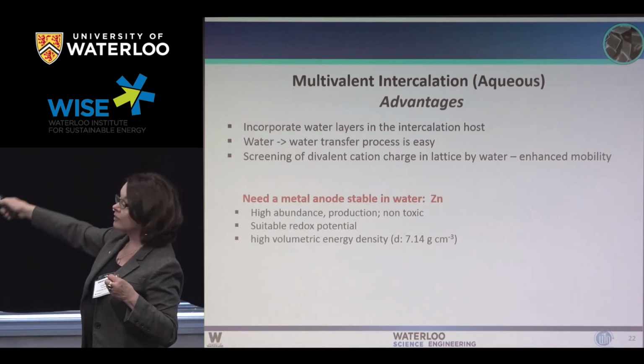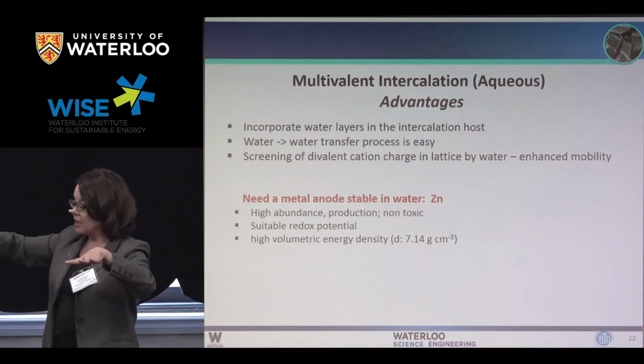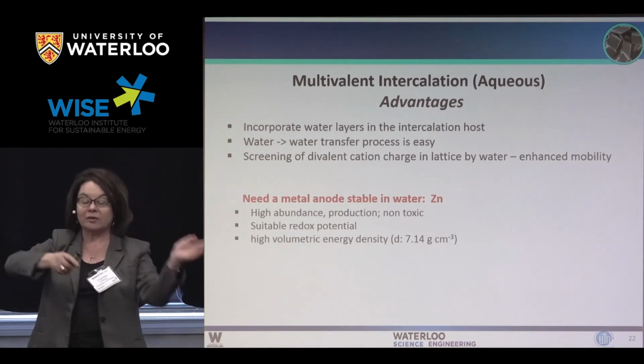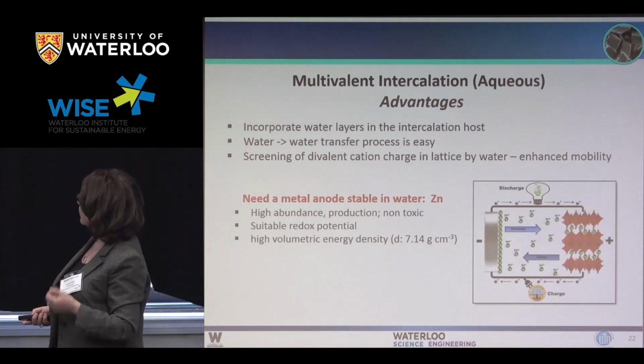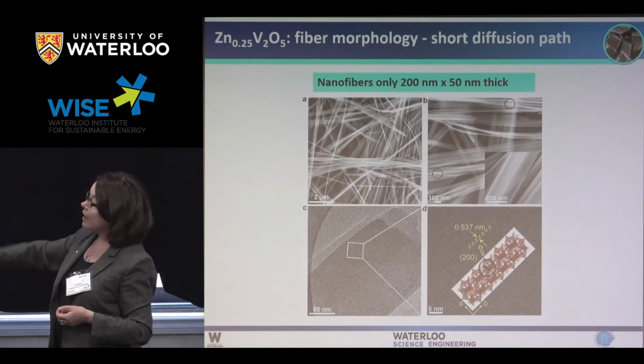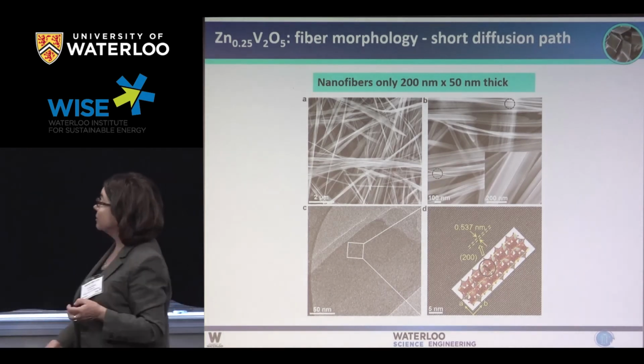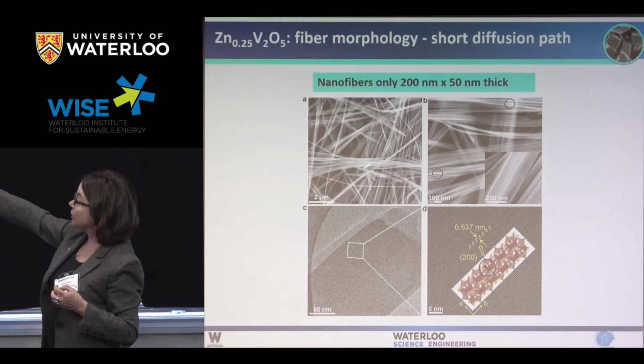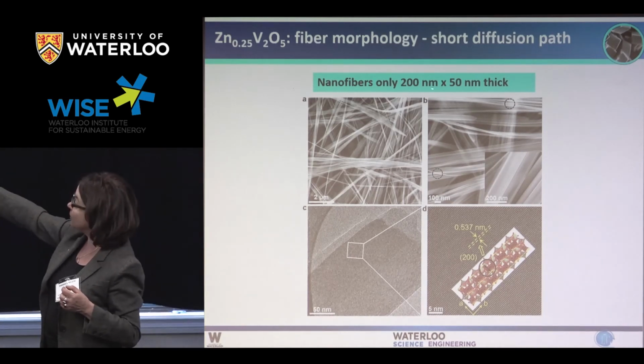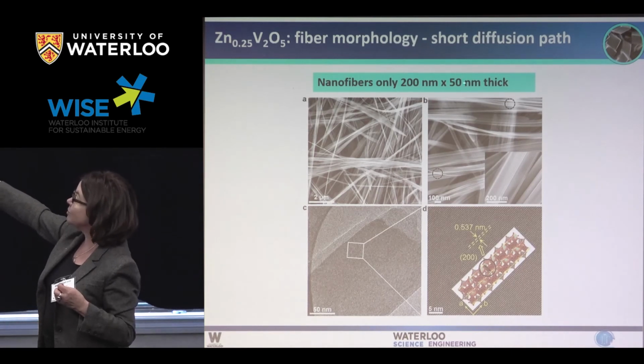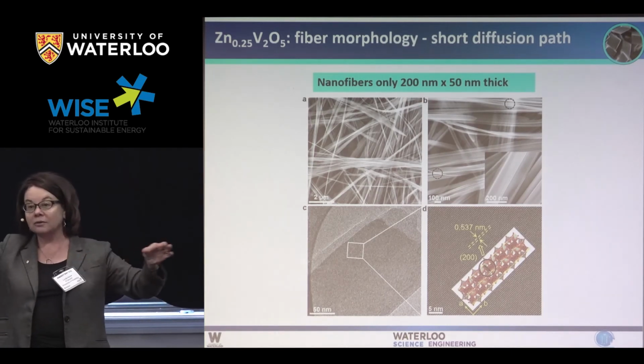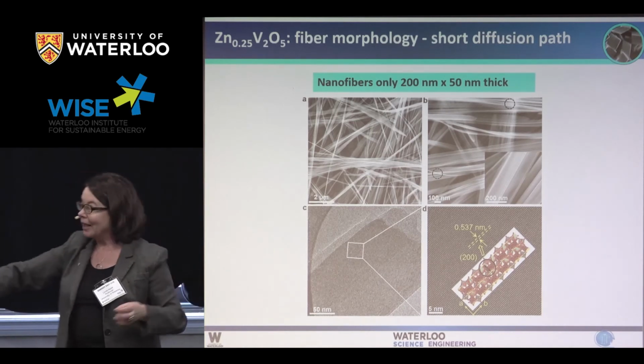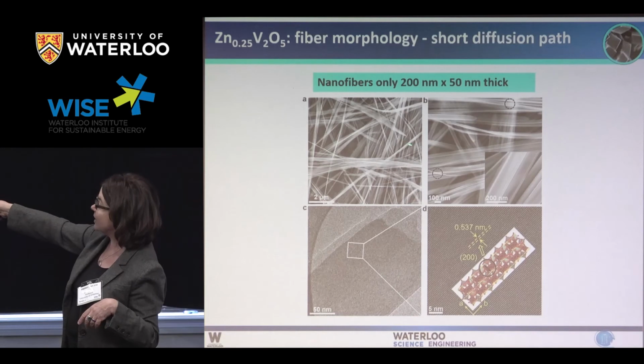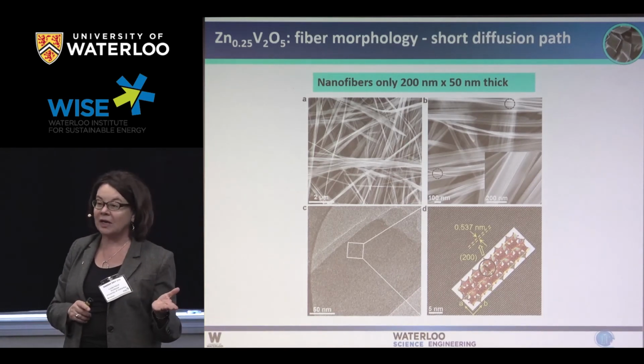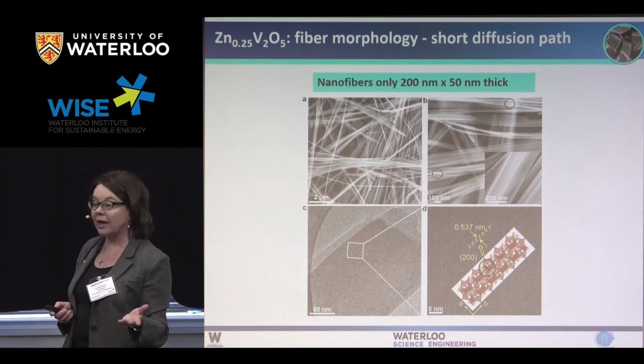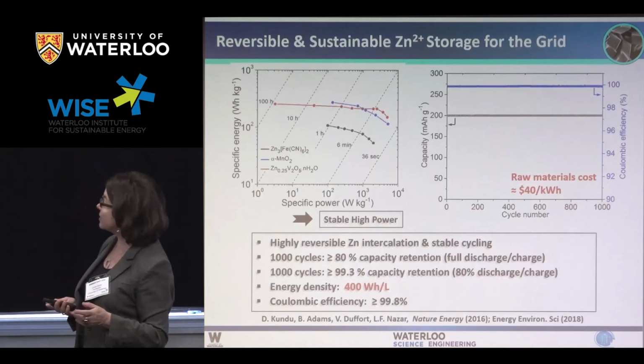And what we're aiming at is trying to develop materials that actually have water in between the layers so that the zinc ion can just move from one watery environment to another. And we've done that with the invention of this vanadium oxide cell. And I'll just end off with a point about how nanomaterials are sometimes critical. These materials, we grow them as long fibers that are microns long, but they're only 200 nanometers by 50 nanometers thick. So they're like long linguine, or maybe spaghettini. The point is that the transport direction is the skinny direction of these fibers. So they transport the zinc ions really well, and because they have water in between their layers, that facilitates the migration of this zinc ion.